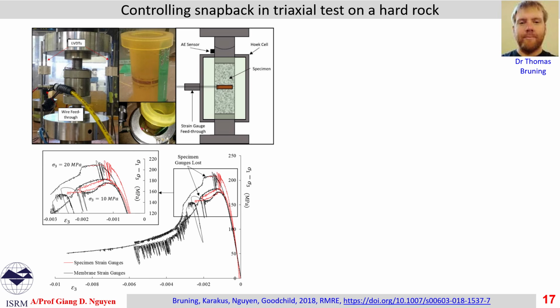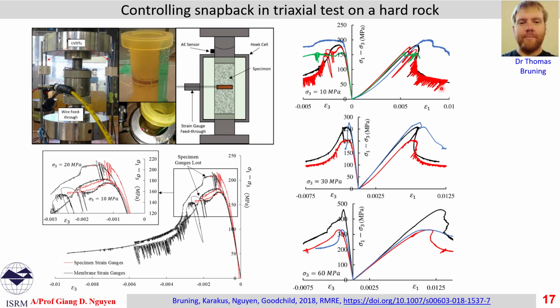The same principle applies to triaxial tests. In this case, we use lateral strain measured by attachments to the membrane for testing hard rock, and we can manage to capture snapback even under sufficiently high confining pressure, say 60 MPa here for a hard rock.